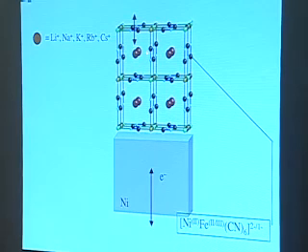So the idea is we want to modify the surface so that we have a surface that no longer generates nickel ions, and now we have, quote unquote, turned nickel into platinum. We have its catalytic properties, and we don't have its corrosion properties. Okay, so we want to shut down the nickel ion generation, but we still need to be able to push charge through this layer, and we can do that through the redox events that are occurring at these iron sites, for example.